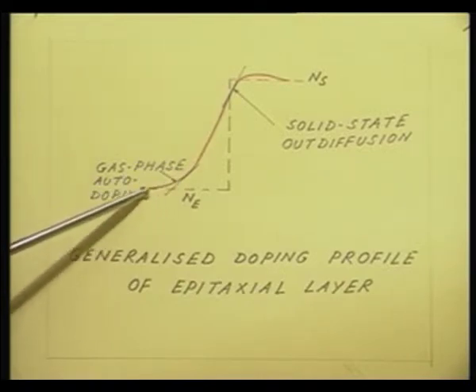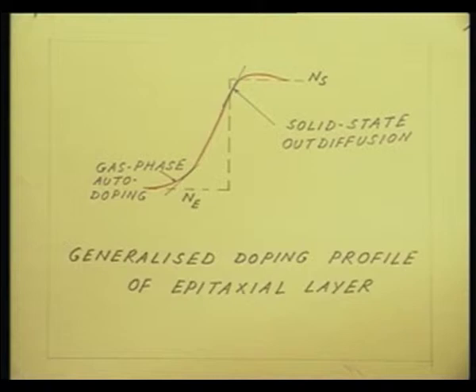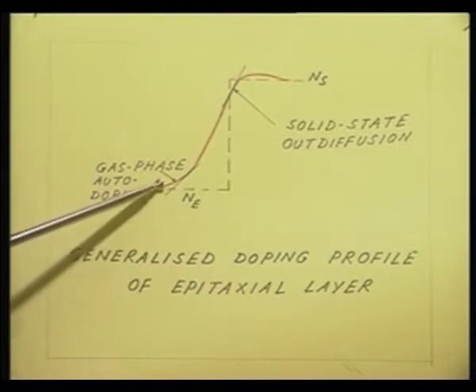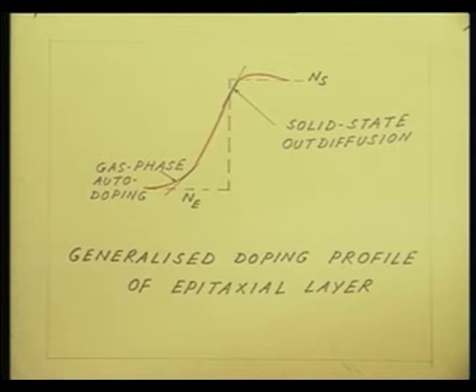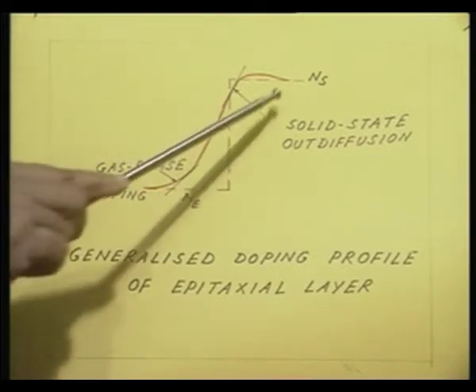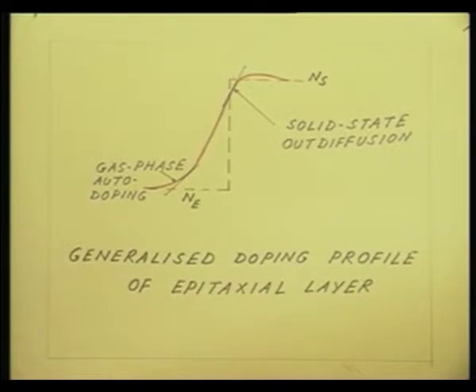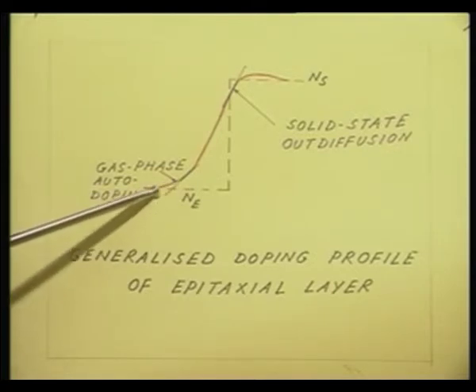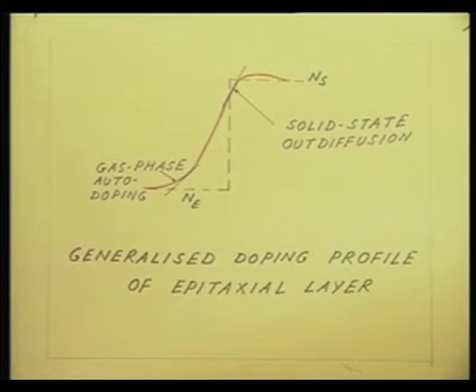But you find an extended tail extending well into the epitaxial region, well away from the interface. You see, this is farther away from the interface, where the effect of solid state out diffusion is minimal. This effect is due to the gas phase auto doping, that is, even before the epitaxial layer growth, a lot of N type dopant has evaporated from the substrate, it has gone and modified the gas stream, and therefore, the doping concentration of the epitaxial layer is affected even farther off from the interface. So, this is how basically the two effects of auto doping is manifested.